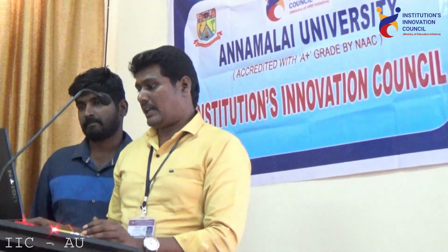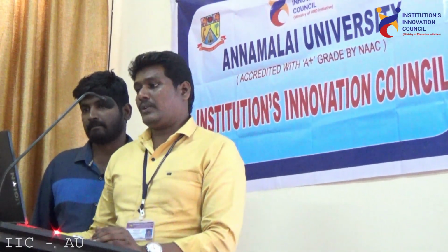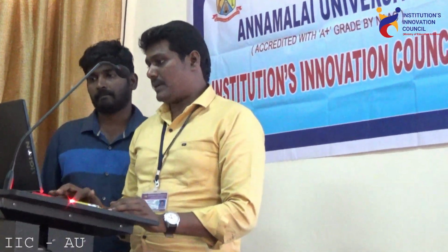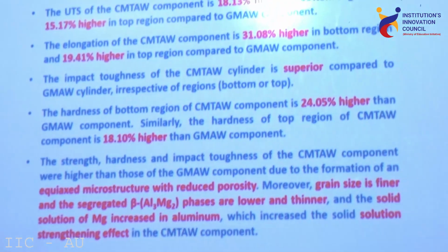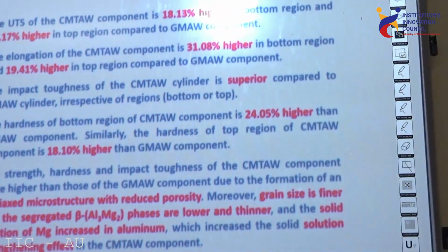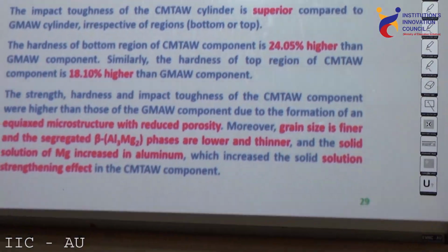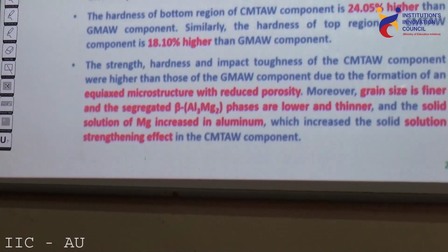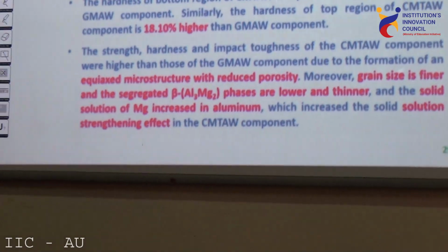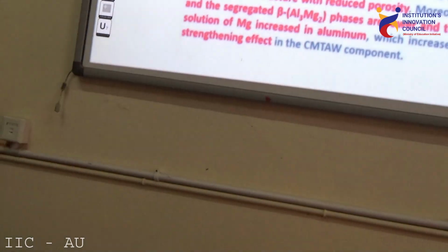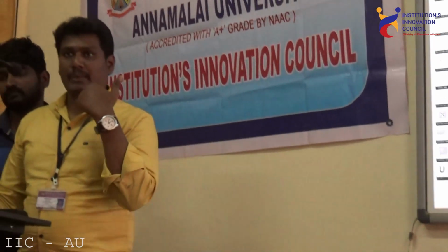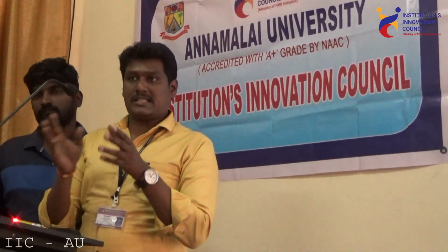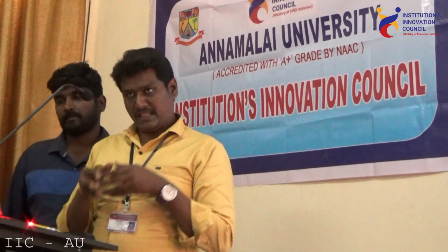So this is the thing that I have discussed here. Conclusion: the UTS of the CMT process component is 18.13% higher in the bottom region and 15.17% higher in the top region compared to the GMAW process, and the elongation percentage obtained is 31% higher and 19.41% higher in the bottom and top region respectively when compared to the GMAW process. And when comparing between the processes, we can conclude that the CMT process has better results than the GMAW process.